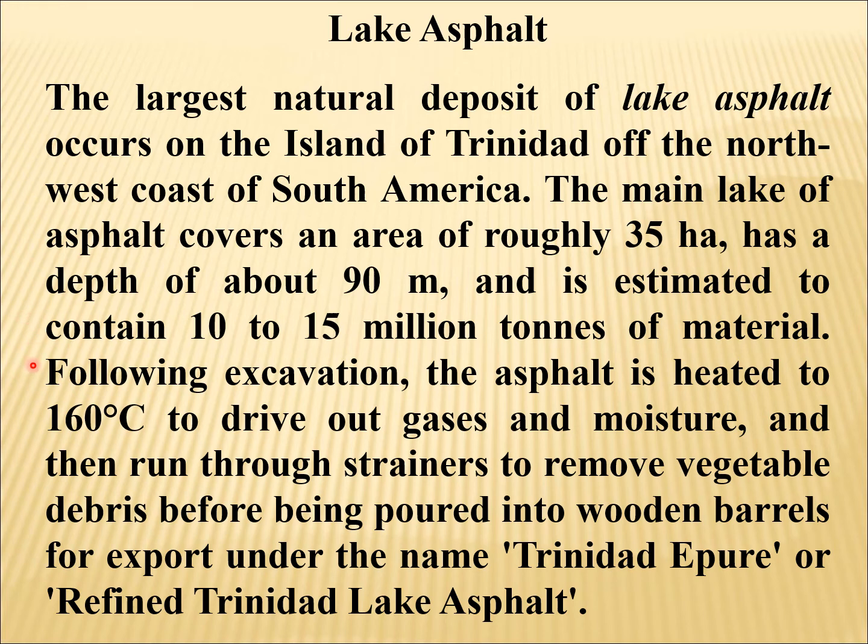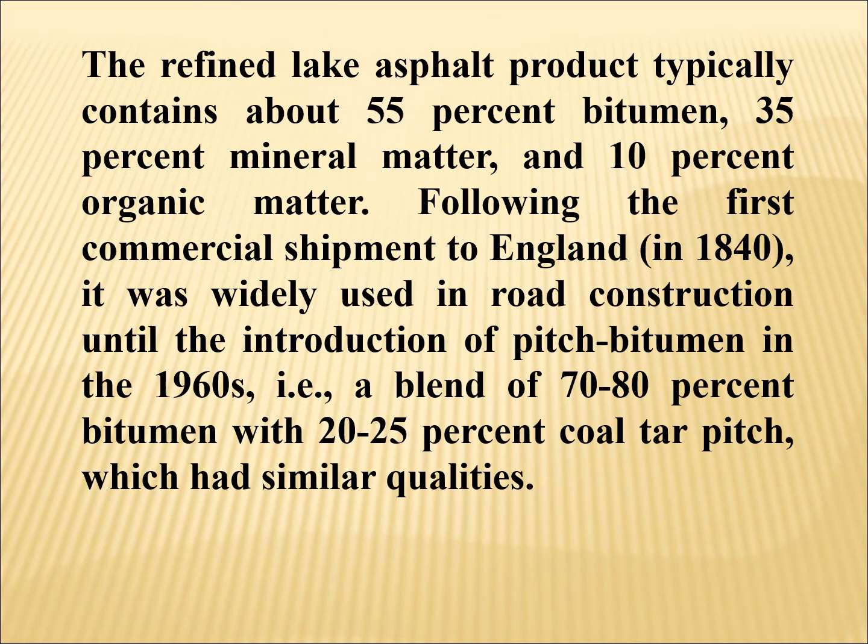Following excavation, the asphalt is heated to 160 degrees Celsius to drive out gases and moisture, and then run through strainers to remove vegetable debris before being poured into wooden barrels for export under the name of Trinidad Epure or refined Trinidad Lake asphalt. The refined lake asphalt product typically contains about 55% bitumen, 35% mineral matter, and 10% organic matter.